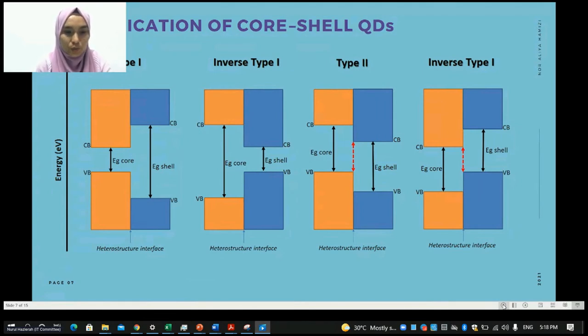The electron and hole of the exciton at the heterostructure interface occupy energy states within the core structure, which corresponds to the lowest available energy separations. The emission wavelength due to the radiative electron and hole recombination or decay within the core is slightly redshifted compared to the uncoated core quantum dot. Examples of these construction materials are cadmium selenide core and zinc sulfide shell, and also cadmium selenide core and cadmium